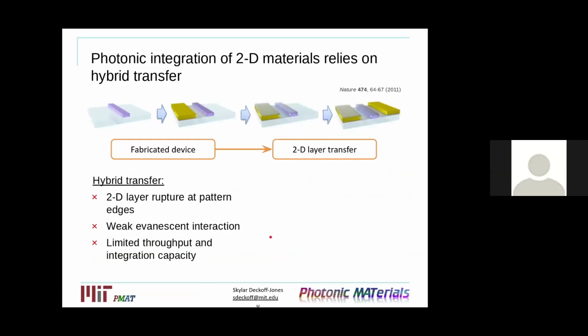And they already have been applied to a lot of integrated photonic devices. However, traditionally, it's done by transferring them onto existingly fabricated integrated photonic devices. So for example, if you start with a silicon waveguide and say some patterned metal contacts, you can then, in this example above, transfer a layer on top of your waveguide and contact to make, say, a modulator. However, this comes with a number of downsides.